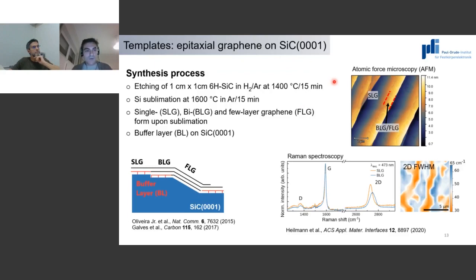Very briefly, how this is grown. So you get a silicon carbide piece. In our case, we have a furnace for that. So it's a 1x1 silicon carbide piece. We load that in a furnace. We first prepare the sample with hydrogen etching at these conditions here. After that, we go for the graphene growth, which basically consists of going to very high temperatures, 1,600 degrees Celsius, in an argon atmosphere.